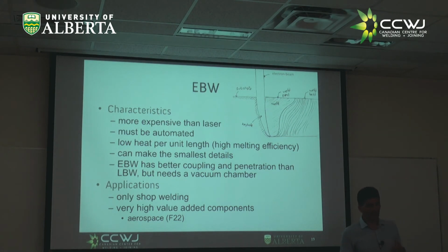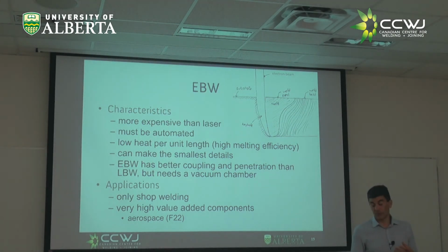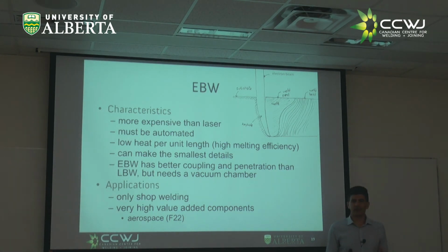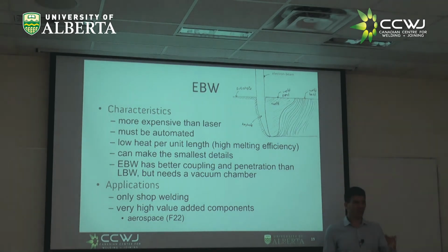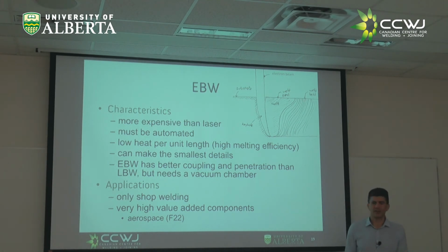So some metals like copper, again, for reasons that escape me, is very reflective to lasers. So welding copper with lasers is not impossible, but it's considered like something that better not. But electron beams go crazy. They don't care, right? You bring in copper or anything else. It's just the electrons coming.